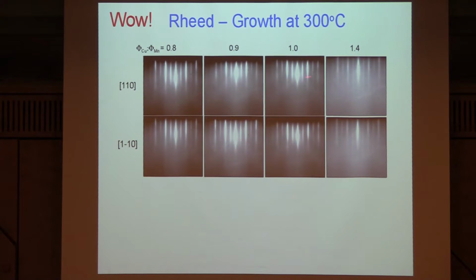Interesting. We also had a look at the different fluxes. We've got a flux of 1-to-1 with the copper and manganese there, 0.9, 0.8, and 1.4, and we can see how incredibly tolerant this material is. It really wants to grow. This stuff really wants to grow.